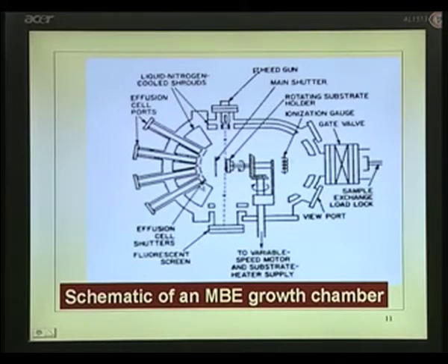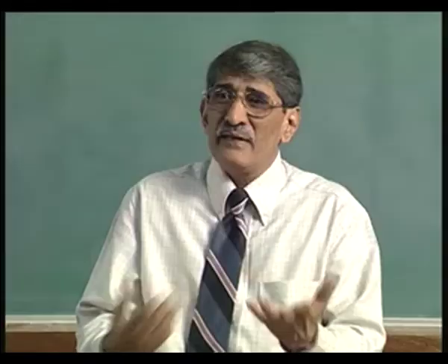The moment you open it, there is a cooling effect. The chamber is not hot, there is a cooling effect. Because of the cooling effect, the beam intensity goes down. So, beam intensity goes down, that is called the fading effect. Now, in the gas source system, the source is outside, you have the control, no fading effect.